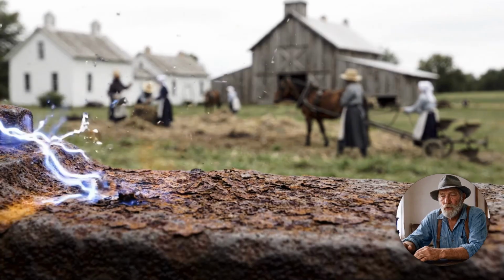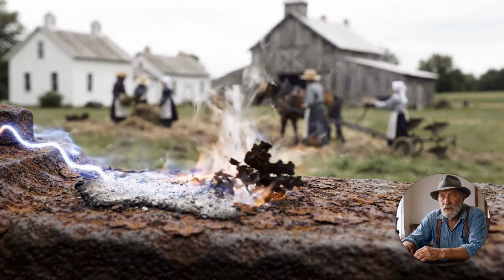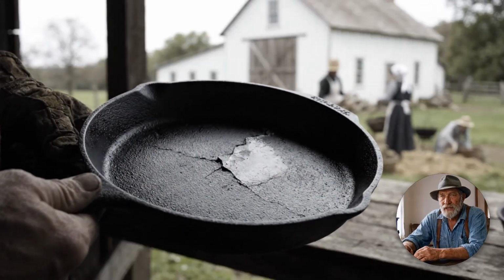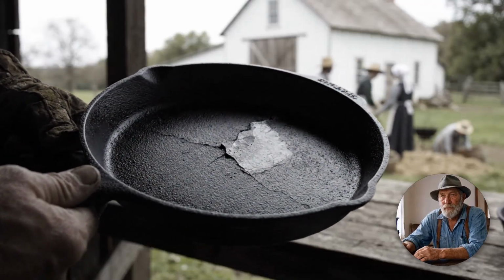Do not run it through your oven's self-clean cycle. That cycle hits 800 to 900 degrees Fahrenheit. Cast iron is brittle, and I have cracked a pan that way. It rang like a bell and split clean across the cooking face.